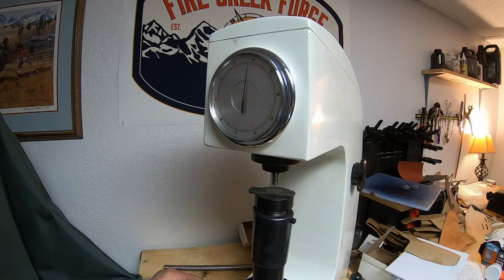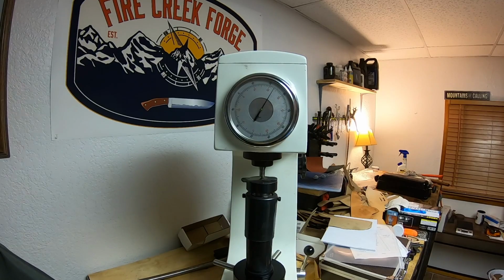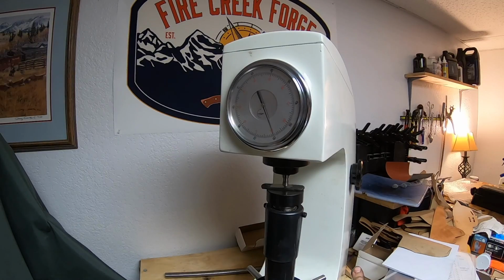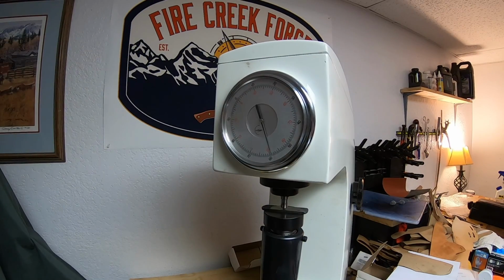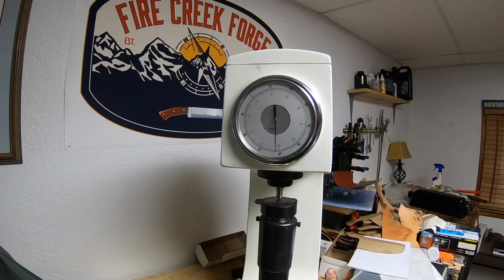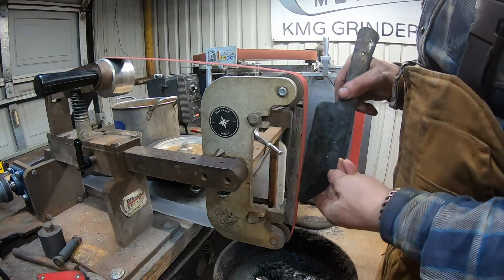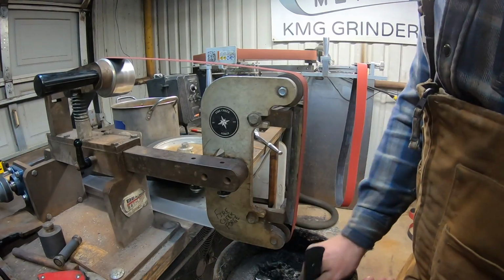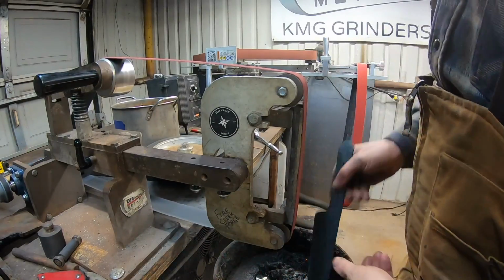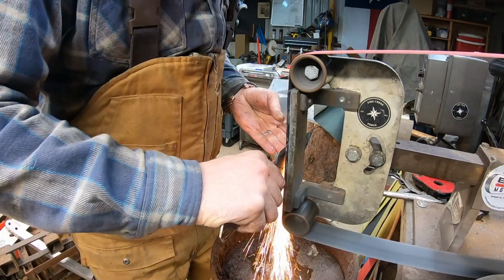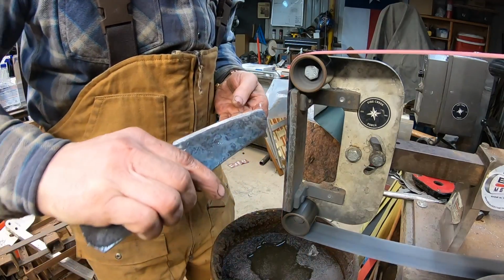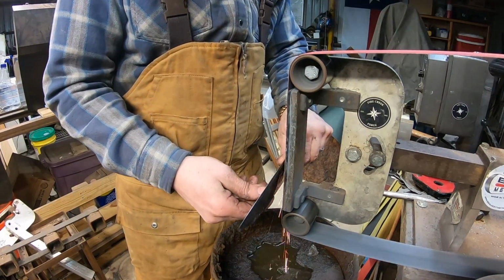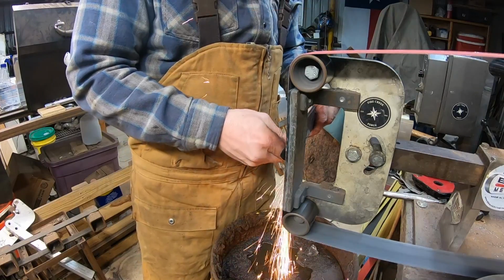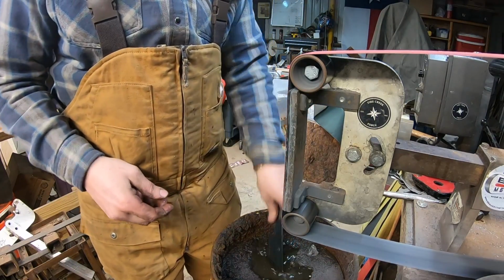This is our test piece, which I ran through the same heat treat processes as the blades. I tested the hardness out of the quench, and strangely, it actually tested 2 points higher after I tempered it for about 10 minutes at 350. I'm not sure why. It might be because it hadn't fully transformed down to martensite, but I need to point out that my Rockwell tester is reading about 1.5 points lower than the actual hardness.